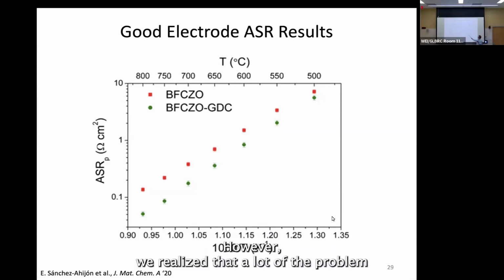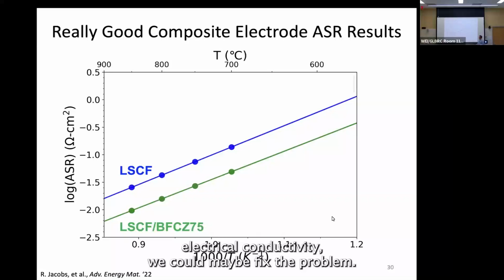However, we did some analysis experimentally with our collaborators at the National Energy Technology Laboratory. We realized we didn't have very good electrical conductivity. So this wasn't a problem with oxygen transport. It was a problem with electron transport. So we realized if we mixed it with something that had good electrical conductivity, we could maybe fix the problem.